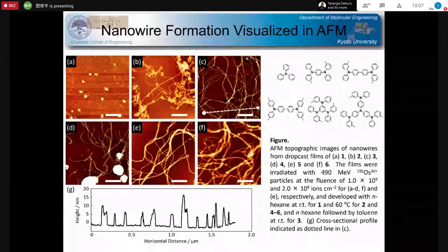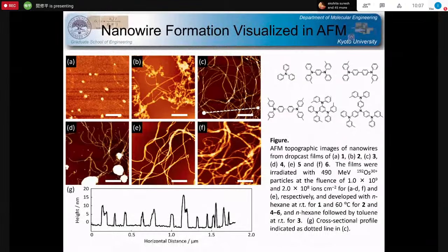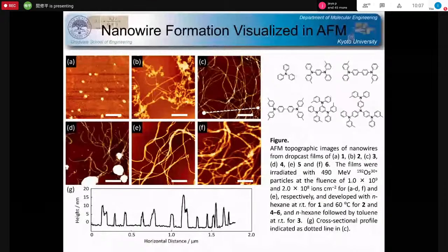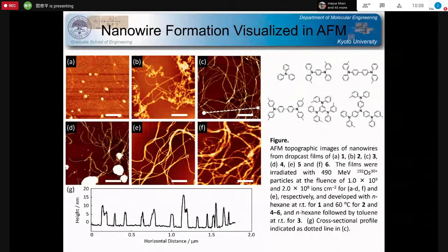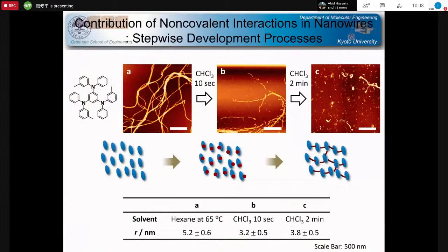As seen in these atomic force microscope images, unfortunately, in the case of the smallest analog of the amine molecules, triphenylamine, in the top left panel, we could not successfully obtain one-dimensional nanowires. But surprisingly, all the other 5 small molecular candidates gave very clear one-dimensional nanowires. So this result suggests an extremely wide feasibility of single particle nanofabrication techniques for a variety of organic molecular systems.